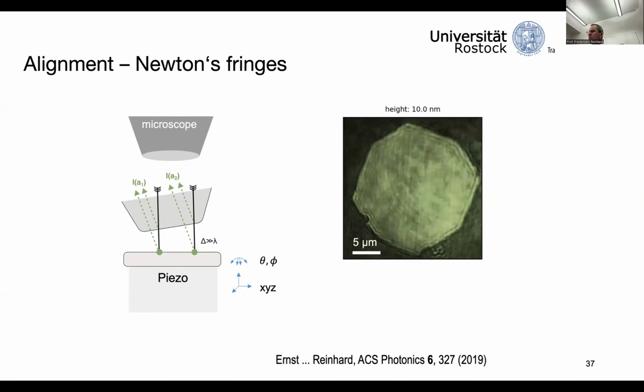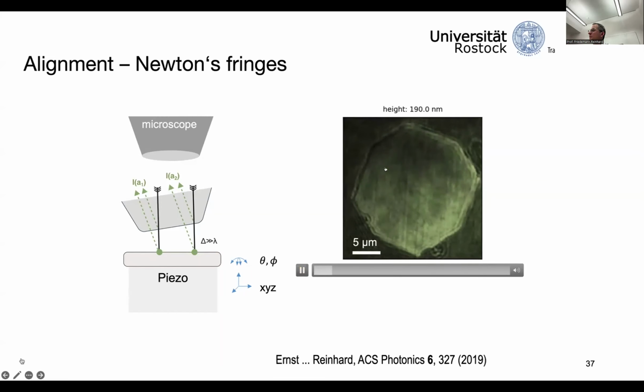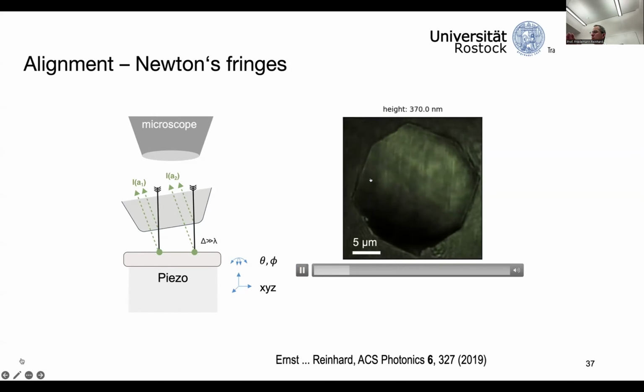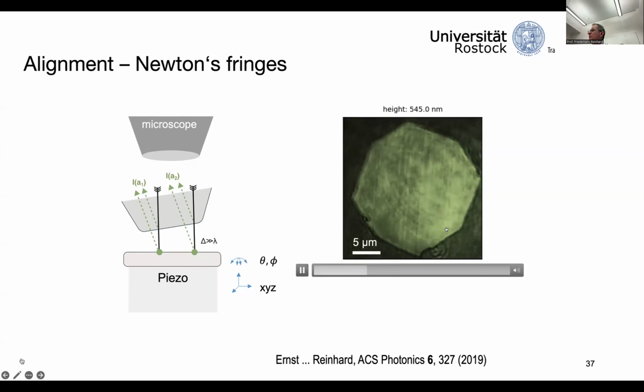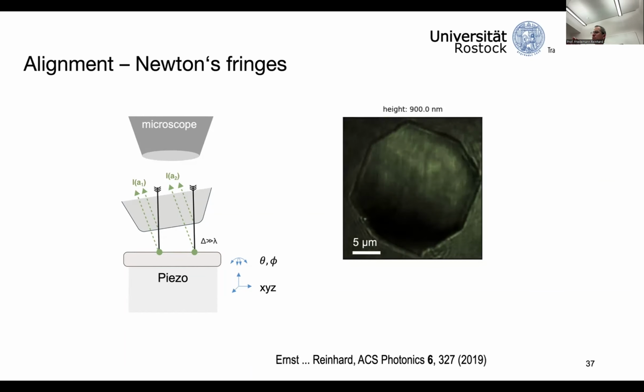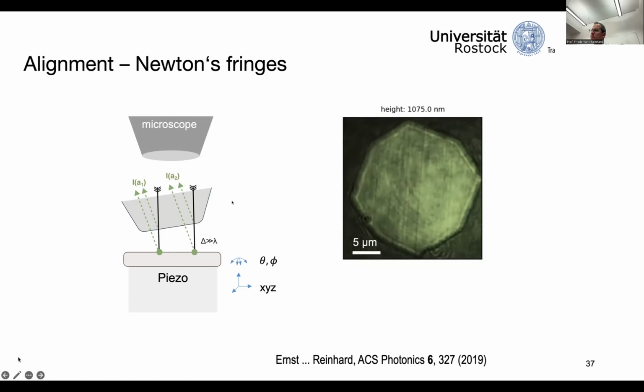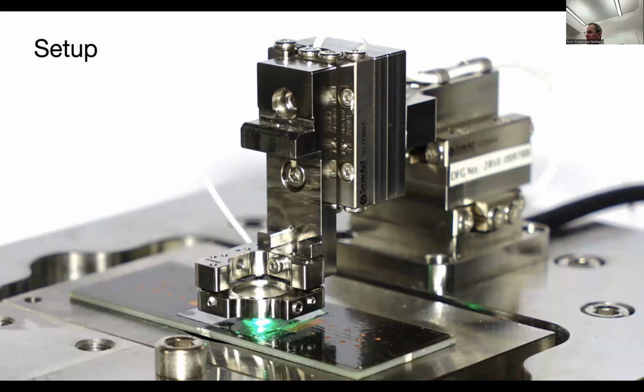Ensuring it mechanically can be easily done by modern piezo positioners, and measuring the alignment to provide a feedback signal for positioning can also be done, for example, by using the sensor-air-sample dielectric interface as a Fabry-Perot resonator. You can observe Newton's fringes. So this is one of the sensors approaching a planar surface, and we scan the height of this air gap between them, and we see dark fringes moving across the sensor every once in a while, which tells us that there is still some tilt between the sensor and the sample, and we can correct for this tilt and ensure perfect alignment. With this, we can actually do scanning probe microscopy in a very compact setup.